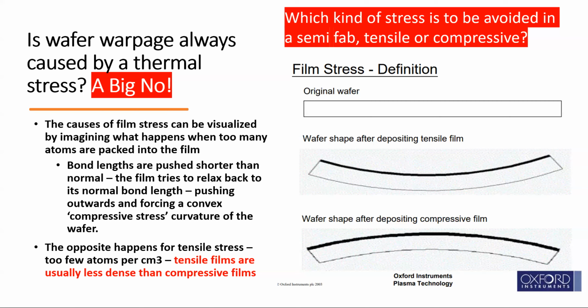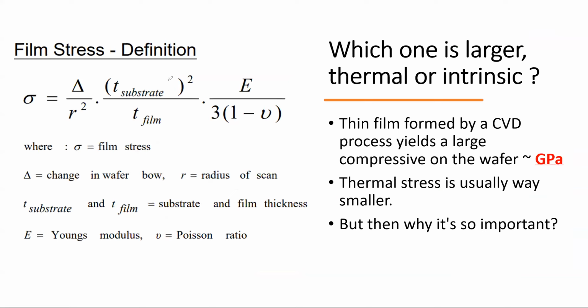And then the calculation of the film stress is done by the simple formula here. It turns out that a thin film formed by a CVD process is usually under large compressive stress on the wafer, usually around a gigapascal. This is what's measured later on. And thermal stress is usually way smaller. Let me show you one example. If you measure a tungsten deposition, you will see gigapascal compressive stress very easily. Any CVD process, pretty much.